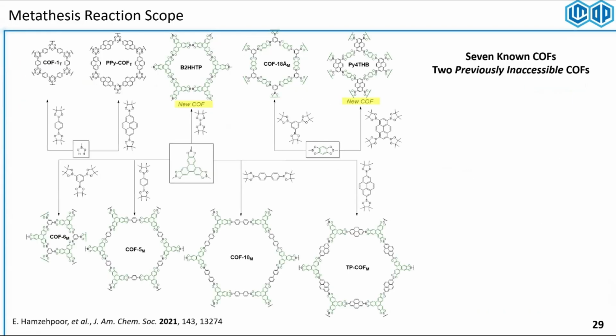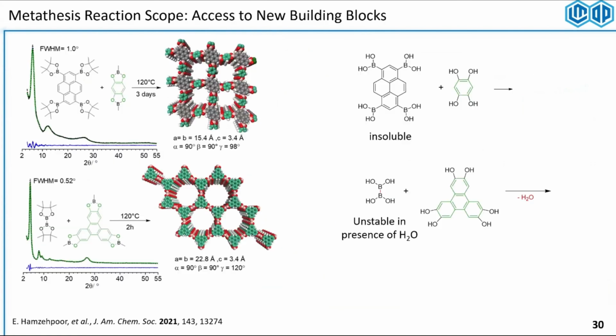So we made a scope of the COFs to show our method is really general, not working with the phenyl boronic acids only, but 2 particular cases we chose to show the fidelity of our methodology. One was a pyrene tetraboronic acid, which is a very insoluble molecule. No one has made a COF before with this compound, even though pyrene diboronic acid was overexploited to make covalent organic frameworks. That's because it has the same issue as the triphenylene, essentially being a very insoluble and impure boronic acid to work with. But using the pinacol, we could synthesize a nice crystalline COF, just like the other COFs that we reported.